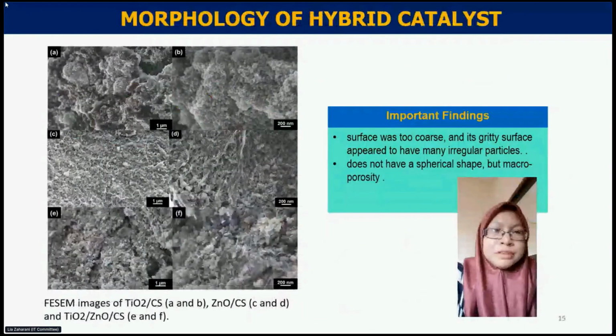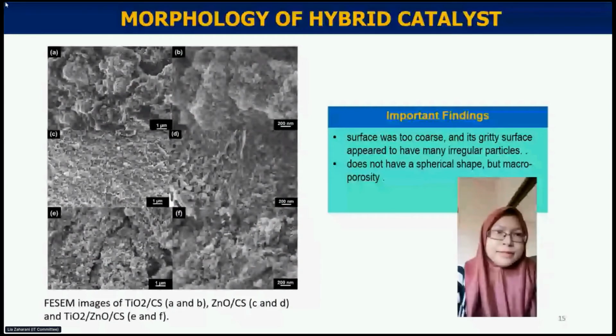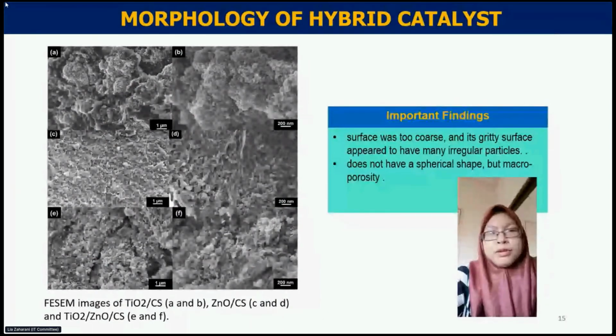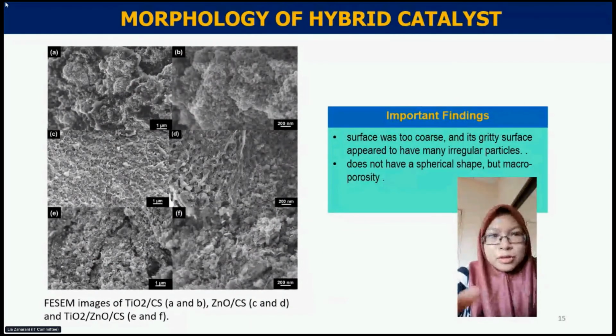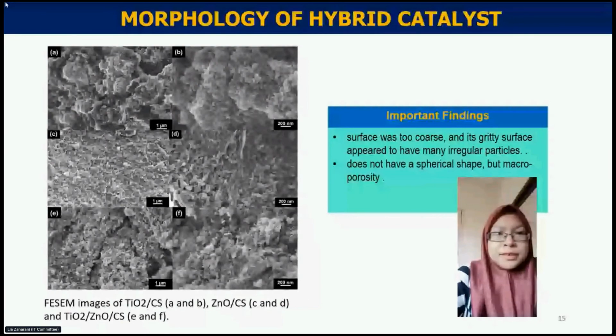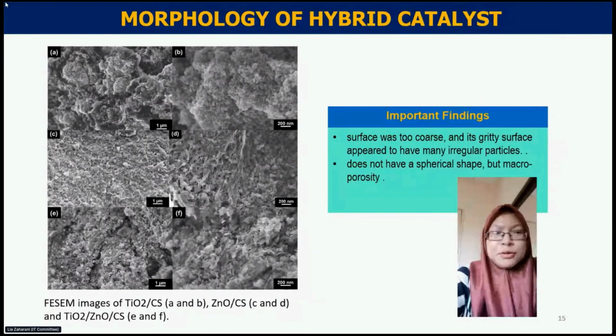The surface morphology analysis of the hybrid catalyst was performed to investigate the dispersion of the zinc oxide and titanium oxide over the supporting chitosan with the field emission scanning electron microscope (FESEM). The image demonstrates that not spherical shapes but a macroporous structure has been observed. The porous structure is attributed to the presence of the chitosan macromolecule, which can be further assessed as the adsorption site during the dye treatment.